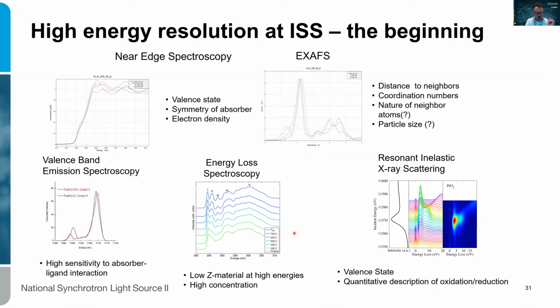ISS was designed to be a high energy resolution beamline, first and foremost, but we spent a big chunk of the first few years doing just regular XANES and EXAFS measurements. And now, since 2020, we are entering this realm of high energy resolution. What it gives us compared to the traditional spectroscopy is a much better sensitivity to the absorber-ligand interaction. It gives us access to low Z materials that are outside of the energy range of the regular hard X-ray beamline. We're also, with things like RIXS, more sensitive to valence states and to all different electronic transitions in the material. So what are we doing about this?